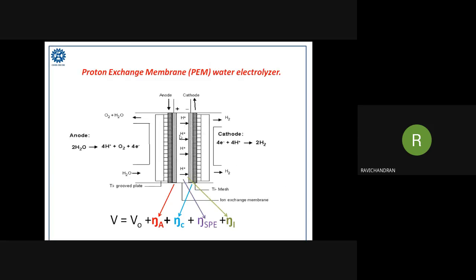We see the overall efficiency depends on the total voltage. This is the total voltage. V0 is the theoretical voltage, so we cannot change it. This is the thermal potential, we can't change it. This is the anode overpotential, which exists on the anode side. And this is the cathode overpotential, which exists on the cathode side. This is the conductivity, not electric, but ionic conductivity of the solid electrolyte. And this portion is called interface resistance, the interface between the solid electrolyte and the solid electronic material.